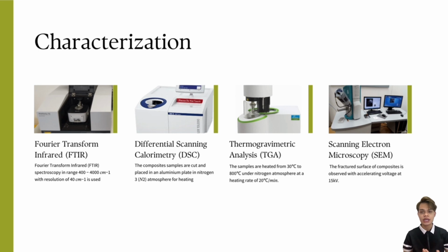To perform the DSC testing, the composite samples are cut and placed in an aluminium pan in a nitrogen atmosphere for heating. The thermal program for the DSC measurement was performed in 3 stages. Stage 1, sample heating in the calorimeter at a heating rate of 10 degrees C per minute from 30 degrees C to 200 degrees C. Stage 2, 200 degrees C for 3 minutes, applied to remove crystalline nuclei. And stage 3, cooling the sample to 30 degrees C in the calorimeter at a cooling rate of 10 degrees C per minute.